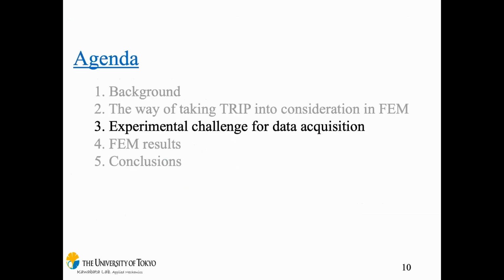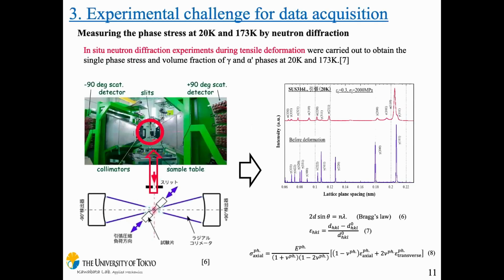And next, I explain the experiment to acquire the data used in the FEM. To use this FEM, the single phase constitutive equation and the volume fraction are necessary. So the in-situ neutron diffraction experiments during tensile deformation were carried out at 20 Kelvin and 173 Kelvin. So in this experiment, we can obtain the single phase stress and volume fraction of each phase.